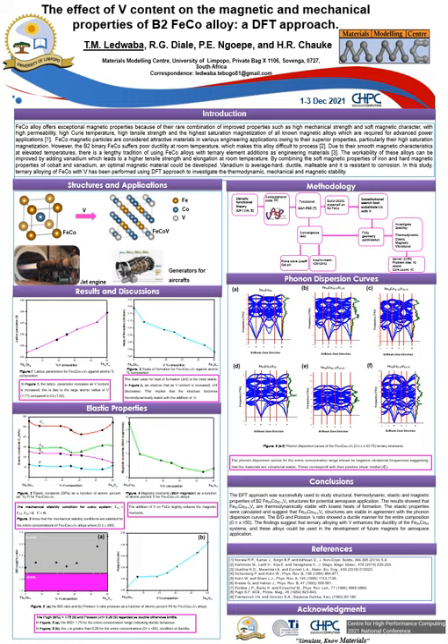Our intention is to use computational methods, in particular density functional theory, to understand how ternary alloying can improve ductility without compromising the magnetic properties. With the help of CHPC servers, we have used DFT employing the VASP code, and calculations were performed considering the GGA PBE functional. Proper convergence was deduced before any of the properties could be calculated.